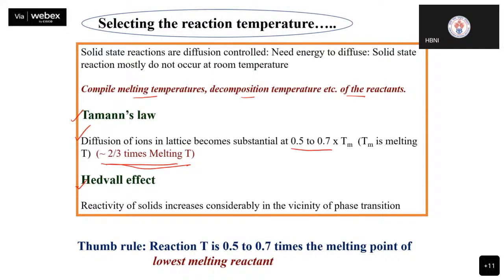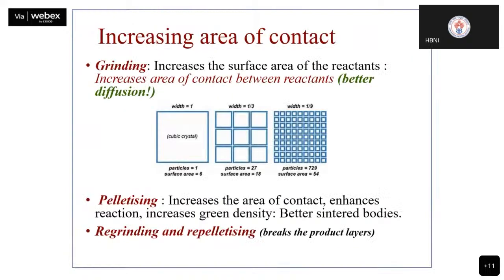And the Hedvall effect states that the reactivity of any solid increases considerably in the vicinity of the phase transition, if at all your reactant is undergoing phase transition. Okay, so when I start planning my synthesis, I look at my reactants, I compile their melting temperatures, then I see which is the lowest melting reactant. And my first heating temperature, as I told you, it's a multi-step process, my first heating step has a temperature anywhere between 0.5 to 0.7 times the melting point of the lowest melting reactant. Okay, whatever reactant melts at a lower temperature, I take 50% to 70% of its melting temperature, and that I choose as my first heating temperature. So this was about selecting the reaction temperature.